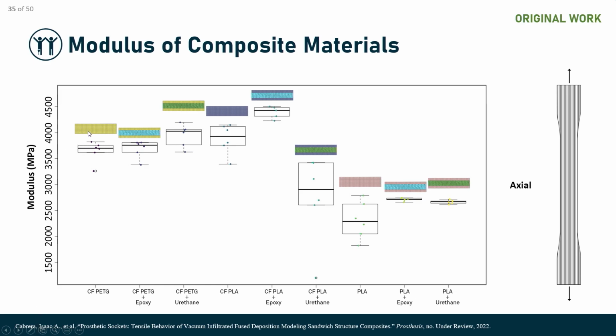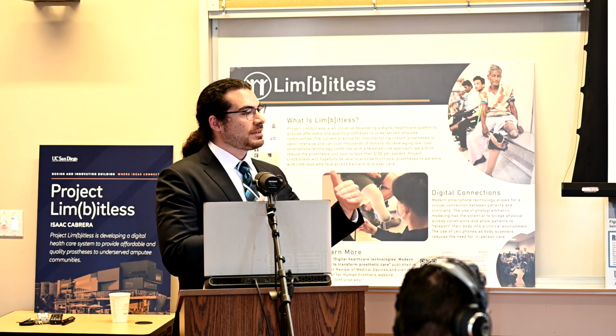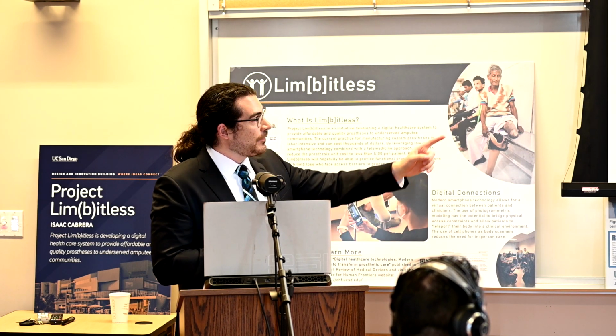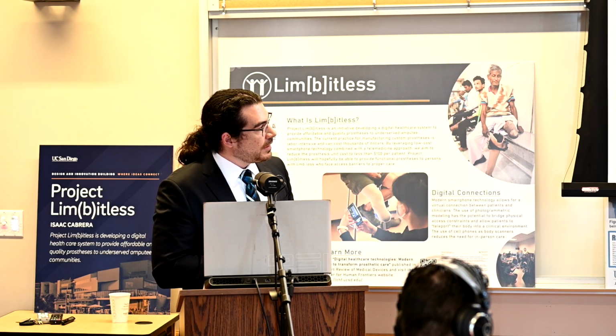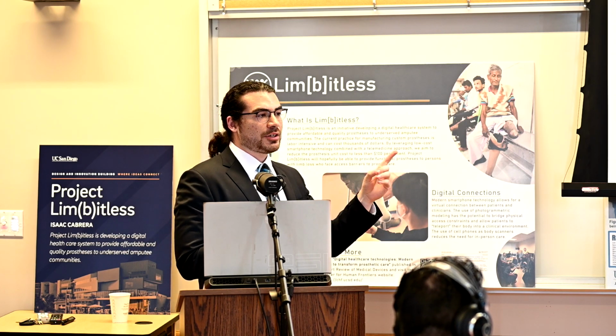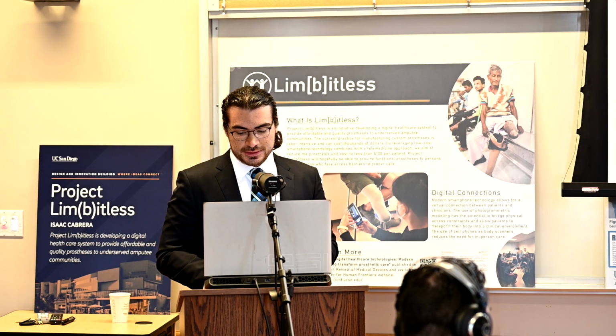So right here, we can see on the left-hand side of each of these figures, we have the standard material without any infiltration, and then we have the two epoxy and urethane infiltrated materials. So when it comes to axial loading, infiltrating with either the epoxy or urethane either did nothing or slightly increased it in every case except for one, which is our carbon fiber PLA and urethane, which actually reduced the stiffness.